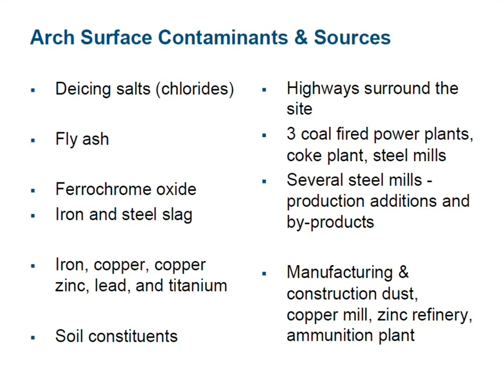Higher concentrations, most of those deposits are fly ash, they're ferrochrome, and iron and steel slag, which are exactly what you would expect from coal-fired power plants, coke plant, steel mills, which were in the area during the life. There were also some scattered iron particles, which you can get from manufacturing sites, some copper and copper zinc. There is a copper mill. And lead, titanium, other things that match with the industry that has been in the area. And then a great deal of common soil constituents, clay, sand, etc., silica.